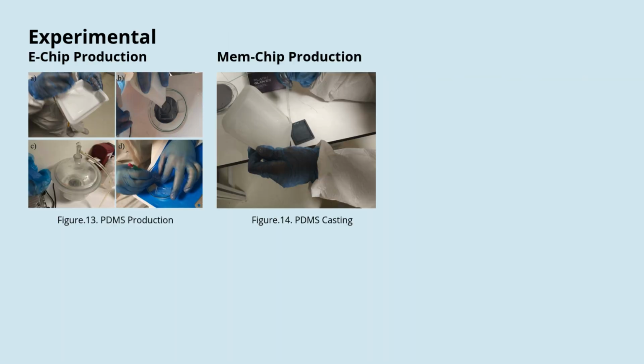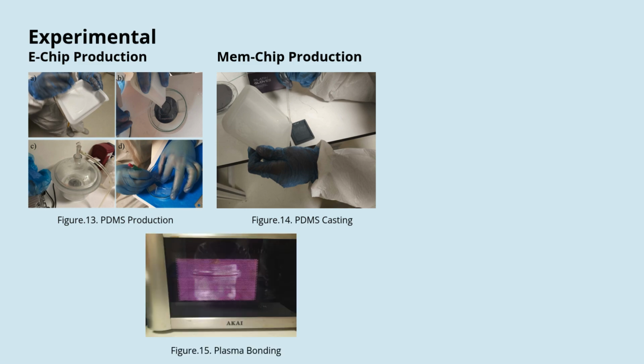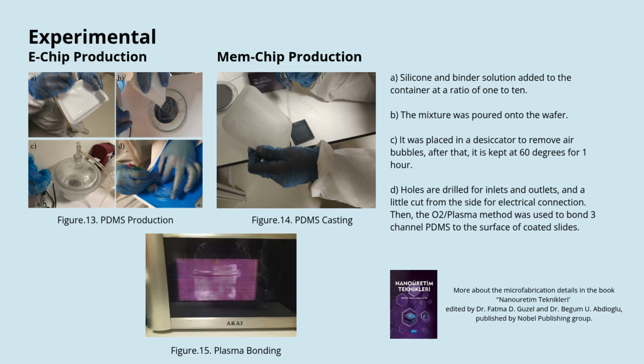Soft lithography steps for the chip production include silicone and a binder solution added to a container at a ratio of 1 to 10. They are mixed for 3 minutes. The mixture was then poured onto a wafer for E-chip and a 3D mold for the MEM chip. The wafer and 3D mold were placed in a desiccator to remove air bubbles for around 40 minutes. After that, it is kept on a hot plate at 60 degrees for 1 hour.